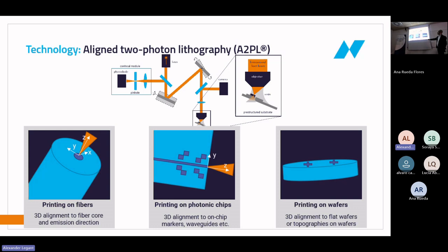Theoretically, without any optical element, you would see the signal, orange, just getting out of the waveguide quite angled, inverted. But of course, that means if you would like to couple that in somewhere, you would have very big losses. That's the reason why I print here an optical coupler, an edge coupler, to have a parallel beam to be able to couple it in somewhere else. And as well, of course, you can print directly on the surface of a wafer.